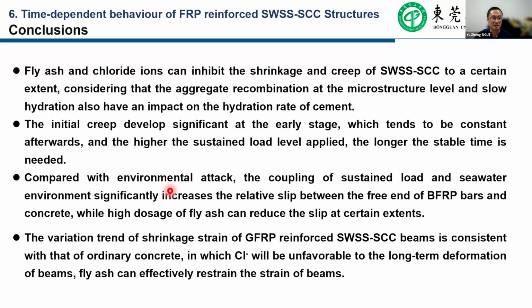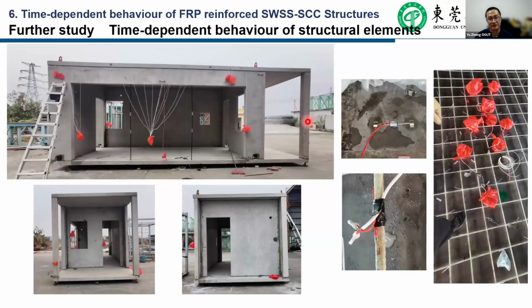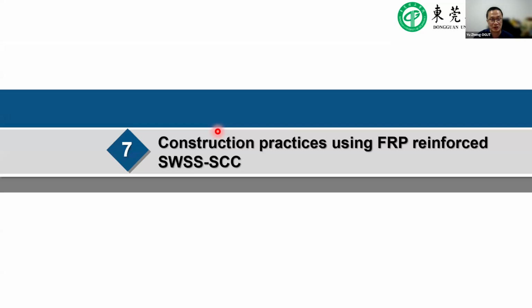Compared to the environmental attack, the coupling of sustained loads and the seawater environment can increase the relative slip between the free end of the FRP bars and concrete. The variation trend of the strain of the GFRP reinforced seawater and sea sand self-compacting beams is consistent with that of the ordinary beams. The second, further study will try to extend this to some real structures.